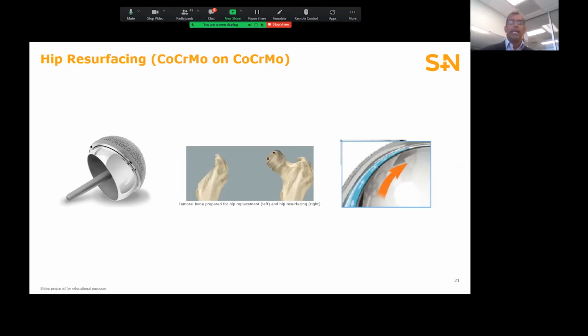Unfortunately, some of these devices had relatively high rate of revision and relatively high wear. In some cases, this was attributed to edge loading and malpositioning. Whatever the case may be, adverse tissue reaction occurred in some cases, and that led to many of these devices being withdrawn from the market. The Birmingham hip replacement device, which originally led to this resurgence, still remains in use as the clinical data for that device is quite good. It's not a growing market segment, but it's primarily used by a subset of surgeons who've had excellent outcomes.